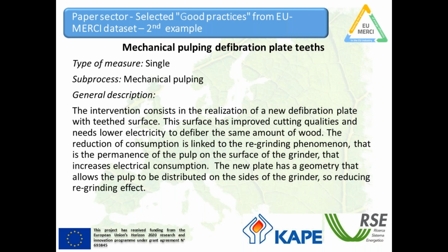Second example, going back in the process, is in the mechanical pulping. It's the installation of some teeth in the defibration plate of the mechanical pulper that avoid the regrinding phenomenon, that is the permanence of the pulp on the surface of the grinder, that increases the energy needed because there is less space for fresh wood to go to the pulper and to be ground. So this new plate allows the better distribution of the pulp on the sides of the grinder, so reducing this regrinding effect.